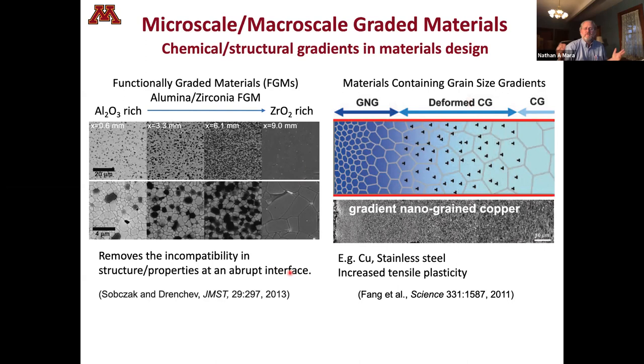It's used in jet turbine engines where you'll have some kind of an intermetallic substrate that makes your turbine blade, and then you want to coat that with some kind of a hard heat-resistant coating. Those are incompatible materials, and so these kinds of functionally graded interfaces have been commonly used there. You can also play games with just the grain size in a material. On the interior of a material, you could have a coarse grain structure. Then you can ball peen or severely deform the surface of the material, and you can refine the grain size to a smaller grain size in this region. And then closest to the surface, where you've really deformed it and refined the grains, you can get very fine grain sizes.